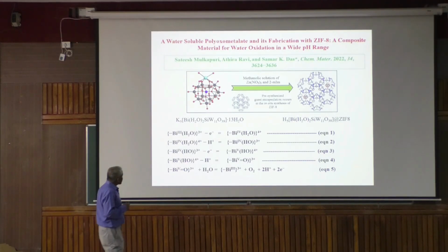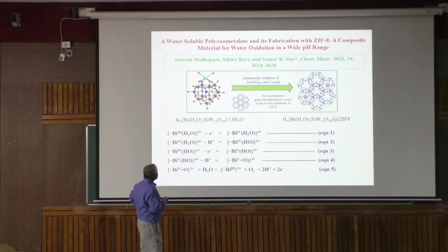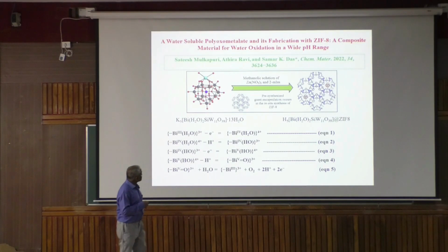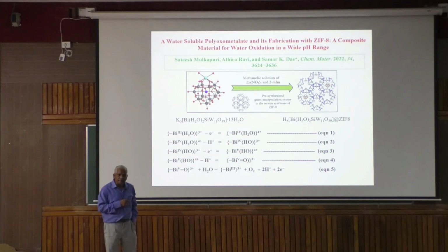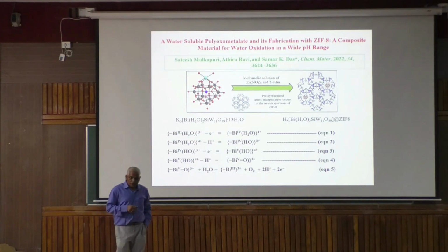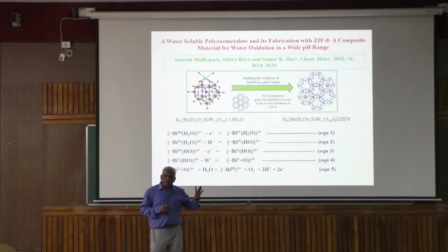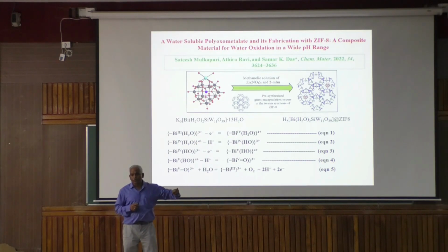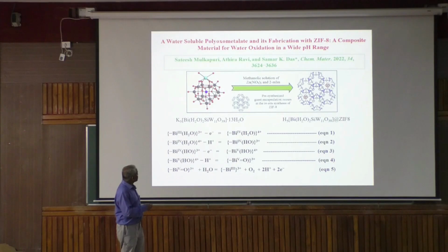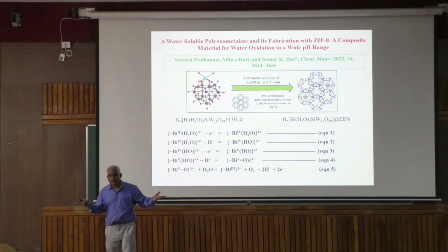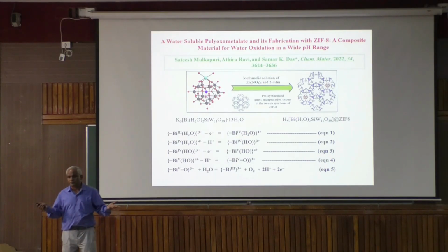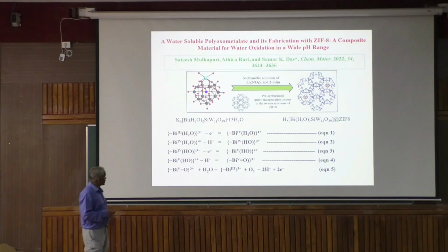So we have kept one functionalized bismuth form polyoxometalate. How did we functionalize with bismuth as well? Why did we do that? The whole moiety is inactive, but bismuth is very active, and we can get water oxidation. Not only that, a miracle happens. The compound which decomposes at neutral pH slowly within 15 minutes or so is stable here forever. Forever means at least weeks and weeks and months and months. Nothing happens once you put it inside.